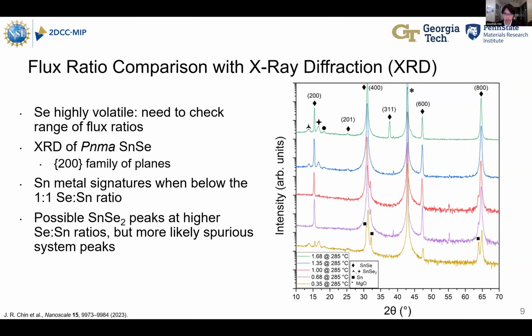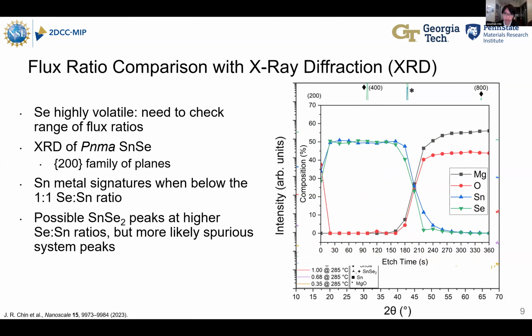One of our initial checks was to determine an optimal flux ratio so that we could access the stoichiometry we need. We're trying to get Pnma tin selenide, which is the one that's going to be piezoelectric. We find that around this 1.35 selenium to tin ratio is a bit of a sweet spot to access the stoichiometry we want. Here we can see some XPS, an X-ray photoelectron spectroscopy depth profile of that sample, where we are maintaining this one-to-one tin selenium stoichiometry through the bulk of the material until we hit the magnesium oxide substrate.